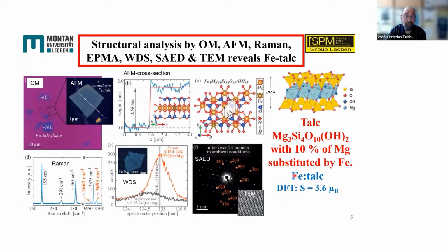And here is, to make a long story short, a summary of our structural analysis: optical microscopy, atomic force microscopy, and Raman, which Lucas explained already. In Raman, we see magnesium, we see silicon, we see OH groups, and we see a very little iron peak that is not shown here in this fingerprint. But from that we deduce, and that is in agreement also with electron probe microanalysis with wavelength dispersive spectroscopy, we have about 10% of iron here, and that is also indicated by this fingerprint, that the OH peak here has a side peak that is due to the iron incorporation.